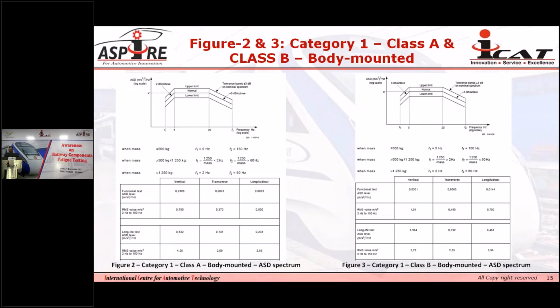One important point that needs to be taken care of while calculating the lower frequency and higher frequency: the mass of only the test sample will be taken here, not the mass of the test fixture. So with the help of this formula, we can find the lower frequency and higher frequency if the weight of the test sample lies between 500 and 1250 kg. Similarly, if the weight of the test sample is more than 1250 kg, in that case the test frequency band is fixed, meaning the lower frequency is 2 Hz and the higher frequency is 60 Hz.